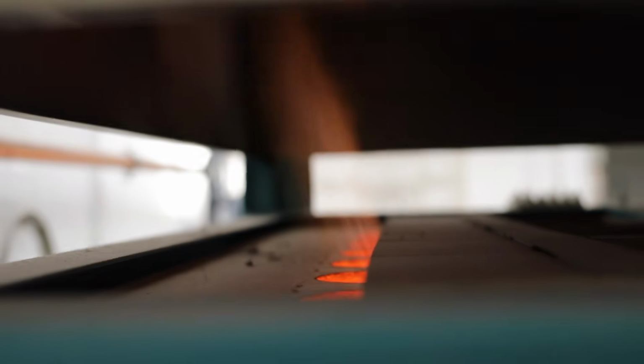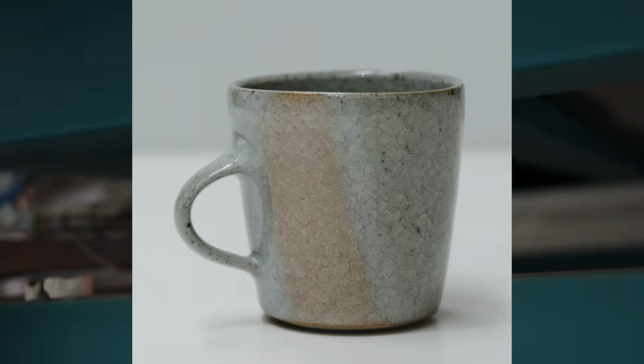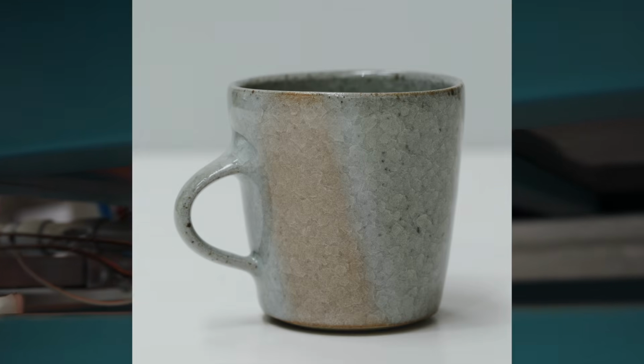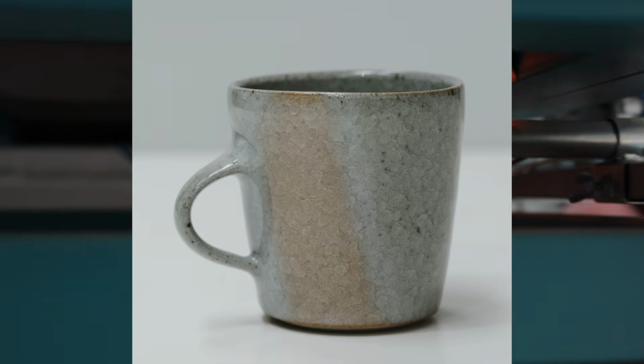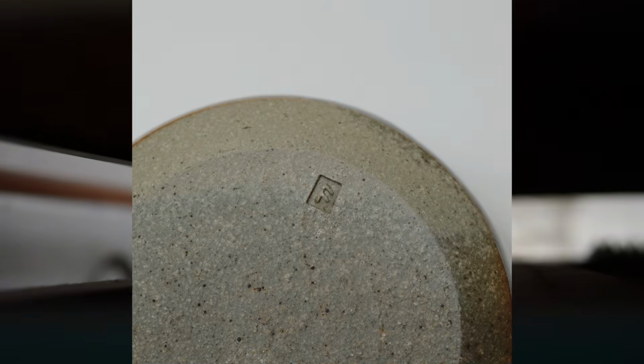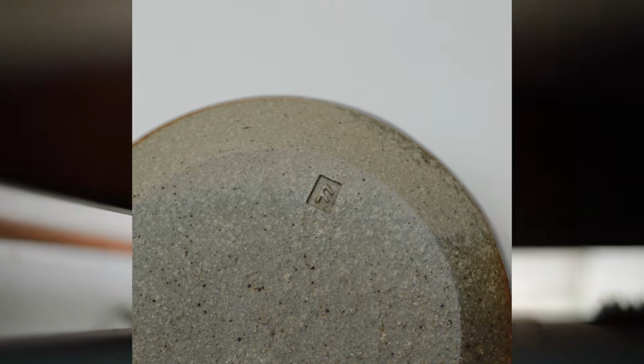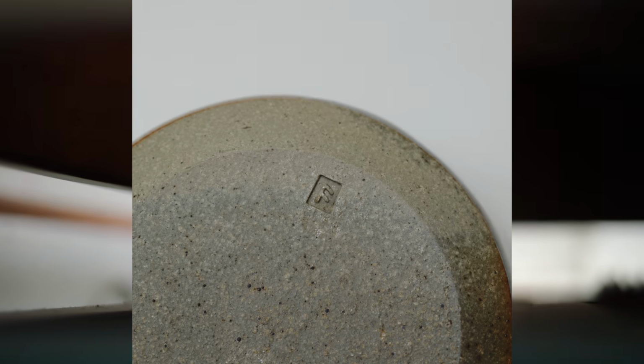If I were to fire these same pots with the same glazes in an electric kiln in an atmosphere which has plenty of oxygen, they will turn a noticeably different colour, like you can see with the white on this mug, which fires in a spot in the kiln which does oxidise very slightly, producing a yellow which isn't too appealing. The clay body fires very differently too, and you can quite clearly see the reduced area below and the oxidised area above.